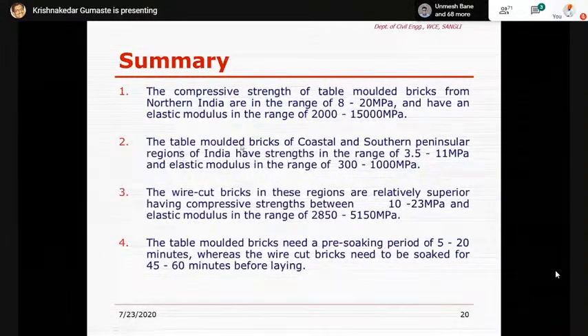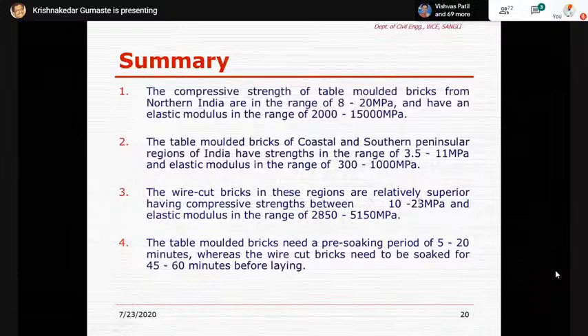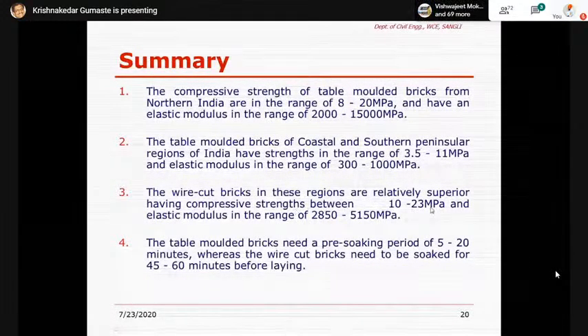The table-molded bricks of coastal and southern peninsular regions of India have strengths in the range of 3.5 to 11 megapascals and elastic modulus in the range of 300 to 1000 megapascals only. The wire-cut bricks in these regions are relatively superior, having compressive strengths between 10 to 23 megapascals and elastic modulus in the range of 3000 to 5000 megapascals.